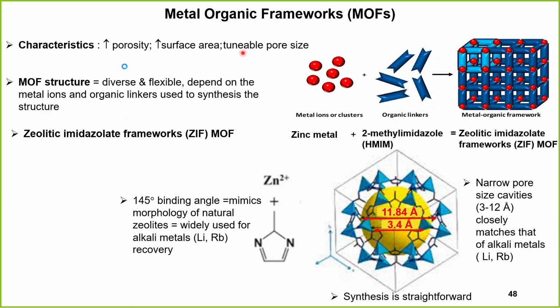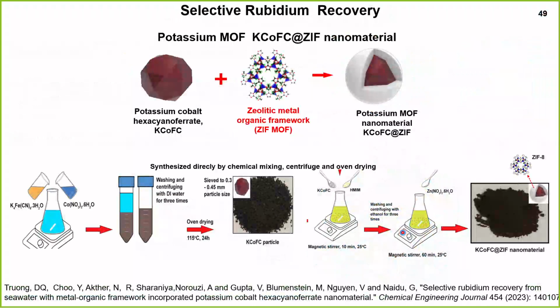And you can see how this metal organic framework can improve the overall KCoFC. We have incorporated this material with both compounds. Based on our experience, the ZIF material has a very specific channel that rubidium can pass through, and the ionic size is very similar, so we can try to maintain it. Then we combined the KCoFC and this MOF compound, especially ZIF, to see how we can improve the overall recovery of the rubidium compound in seawater.